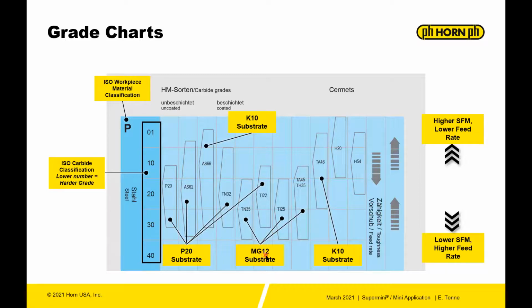You can see here MG12 substrate. You can find that anything that ends in a 5: TN35, TI25, TA45, TH35. Since they end in 5, that's an MG12 substrate. And then in addition to the classification, the number, you can see that on this side you have toughness and feed rate. So if you have higher SFM needs, you will have lower feed rate because you're going to have a harder carbide. Harder carbides are able to take more cutting speed, but then they're more prone to chipping. Lower SFM can have higher feed rate because they're more ductile, so you can put more pressure on the cutting edge without it chipping.